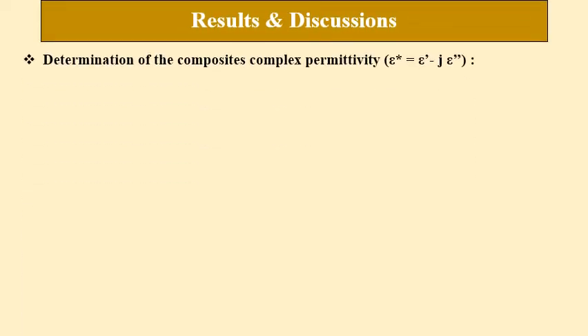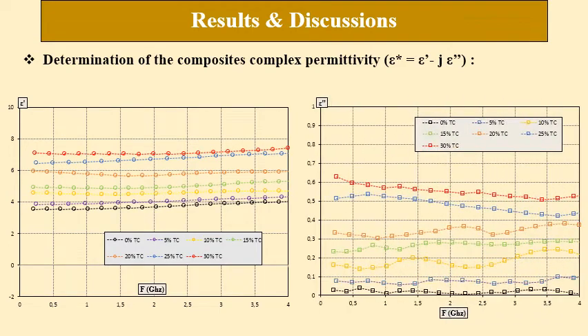Now, results and discussions. In this section, we first talk about the determination of the composite's real and imaginary parts of permittivity. In the figure of the real permittivity part variation as a function of frequency, we notice the increase of the real part as the volume fraction of calcium titanate increases. For the imaginary part of permittivity figure, we notice that amplitude spectra are almost constant for low frequencies.